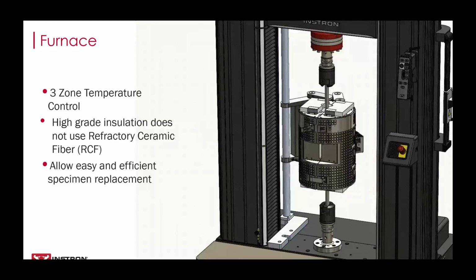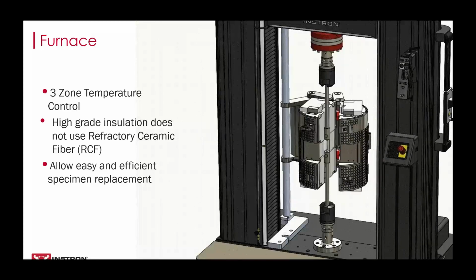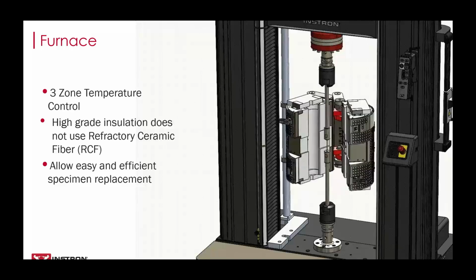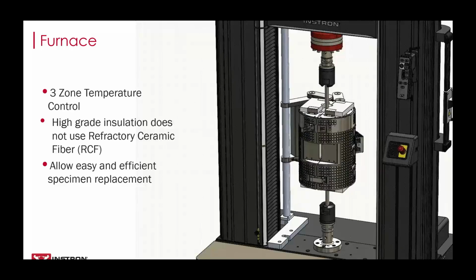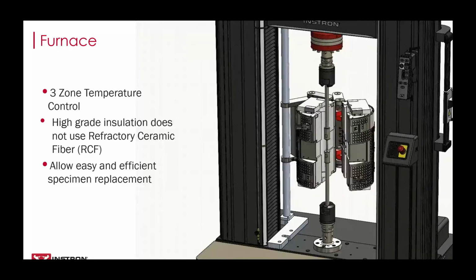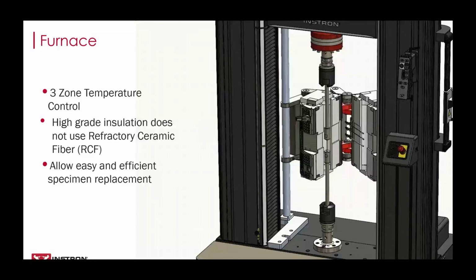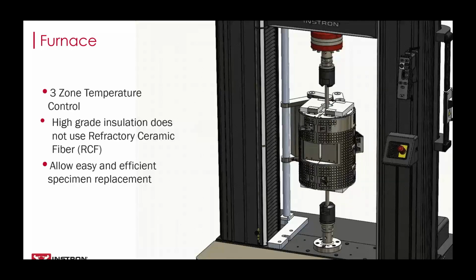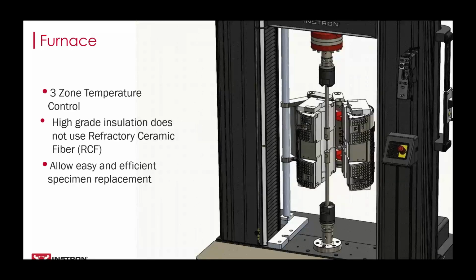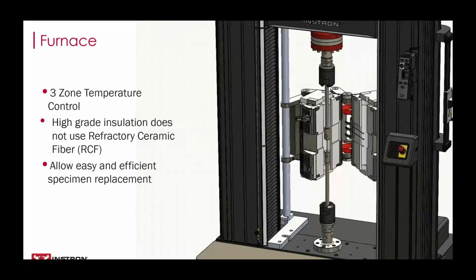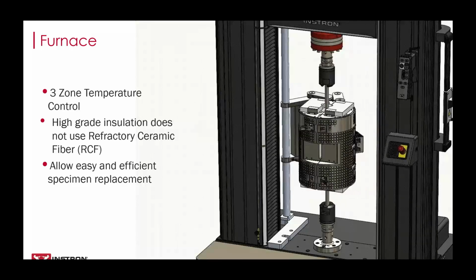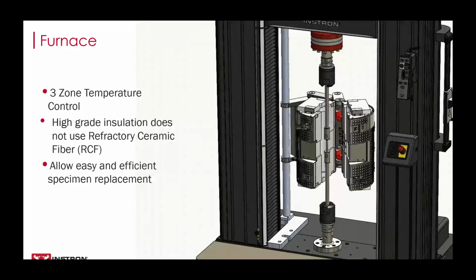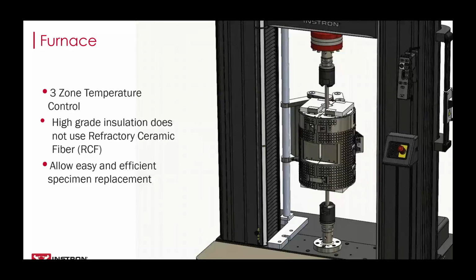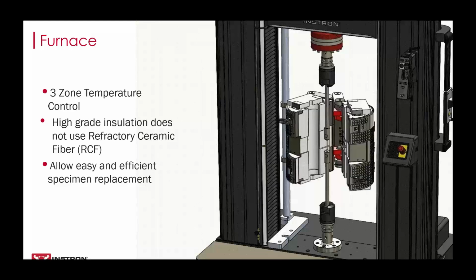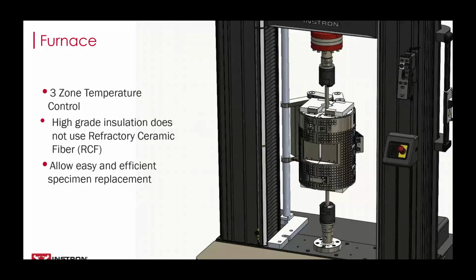And finally, wrapping up with the last part of the puzzle, you have your furnace. Instron offers a three-zone furnace with a front extensometer entry point. Each zone is controlled with a Type K thermocouple that is mounted to the center line of each zone. These can be individually set and controlled. Safety was definitely a priority when selecting this design. The entire exterior of the furnace has a heat shield to protect the operator from the extreme temperatures inside the furnace. Ceramic insulation lines the furnace's interior with ceramic blocks at the top and the bottom of the furnace.